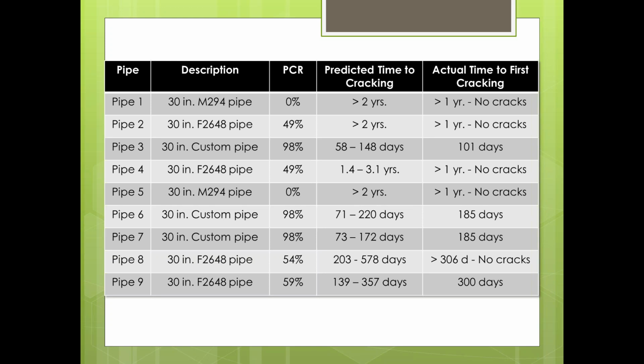Keep in mind, these pipes were deflected at a very high level, upwards of 20% deflection. And many of these were designed to fail in a fast fashion as well, with very poor stress crack resistance, specifically designed so that we can actually validate that the modeling being done can happen, because otherwise this testing would have been going on for many, many years, and there's budgets to everything.